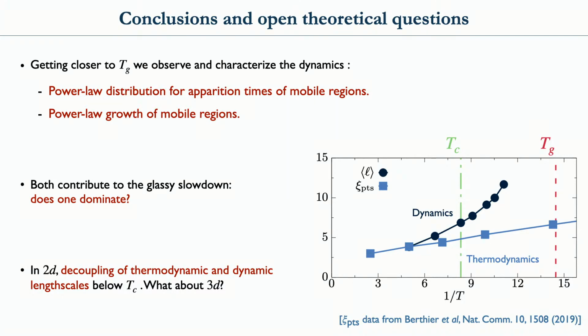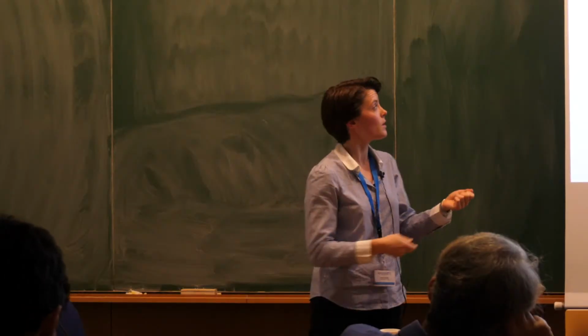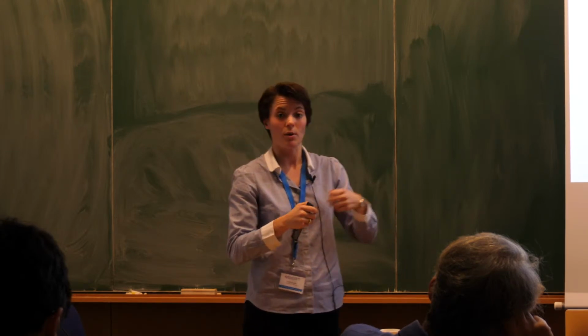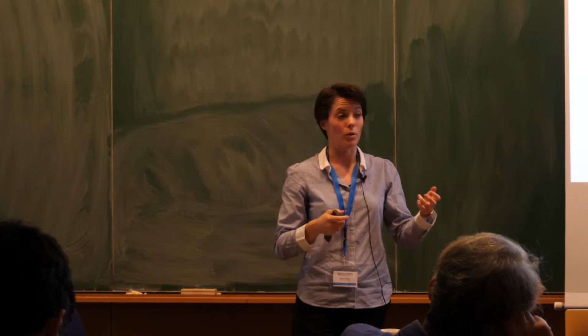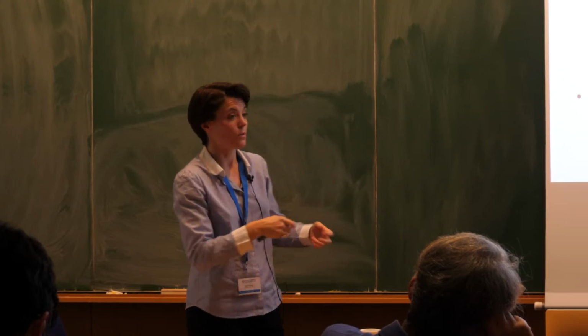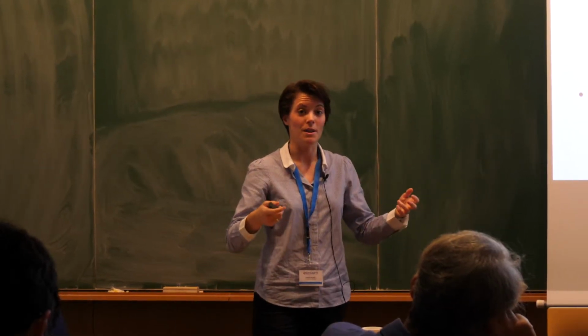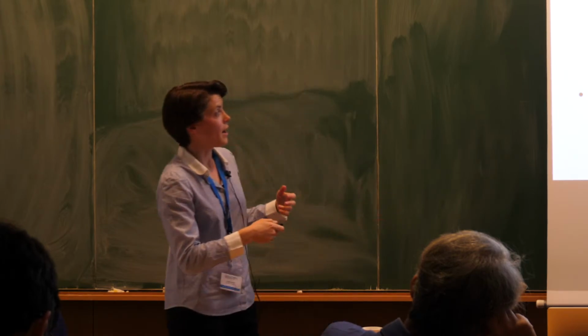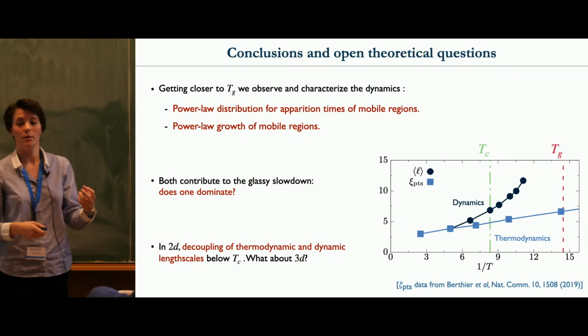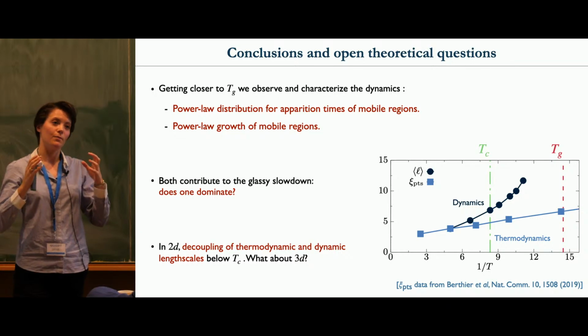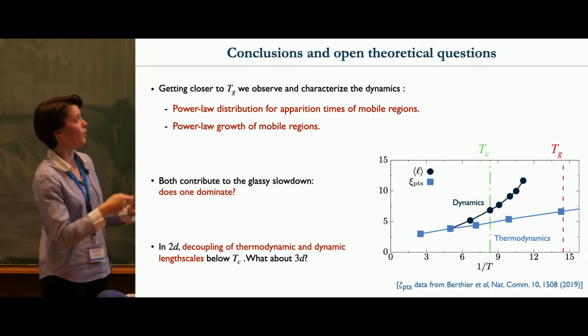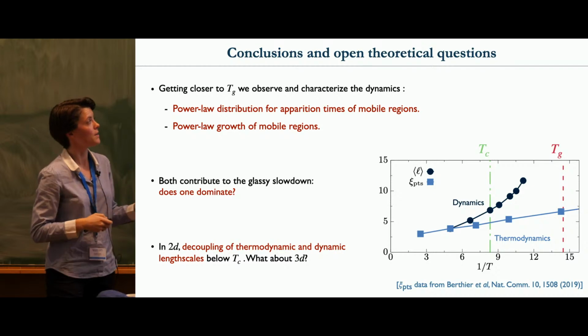So we have two effects basically in the slow dynamics, and both change with temperature, so both the apparition of the clusters and their growth. So there are mainly two reasons for which the dynamics can slow down. First one is the distribution here gets increasingly broad, and this is in part what we observe. And the second thing is that once these clusters appear, they grow increasingly slowly. So the question I would say now is maybe a bit clearer, it directs the effort on these two questions in terms of characterizing the dynamics.